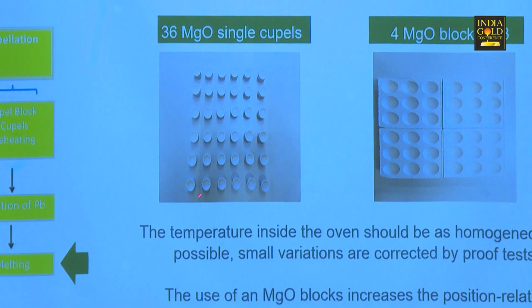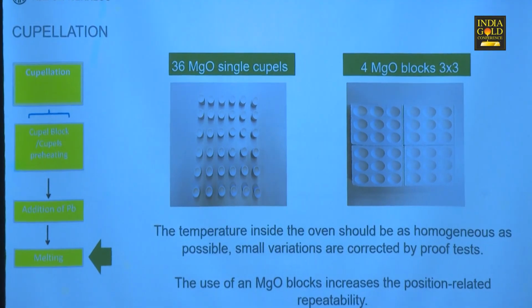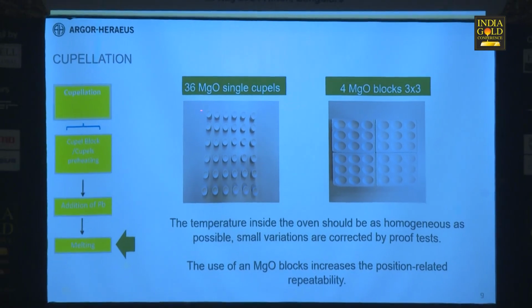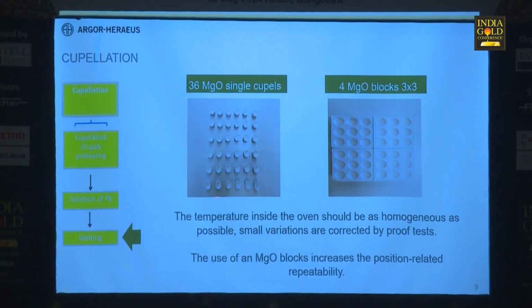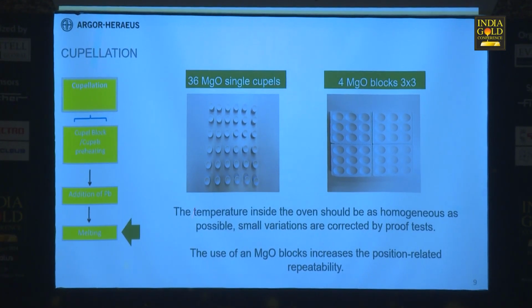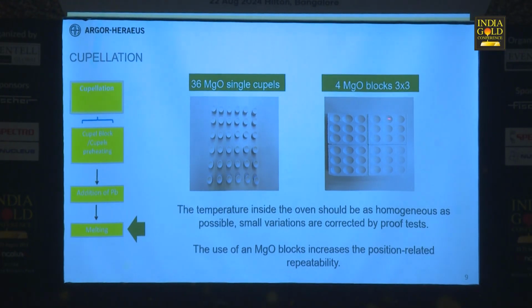Normally, in my laboratory, when we use single cupels, we put the proof test here, here, here, here, here, and here. This is because we have a little difference in temperature from the bottom to the top, from the right to the left. In this case, if you use these blocks, it's easier to put the proof tests in the same line because of perspective.